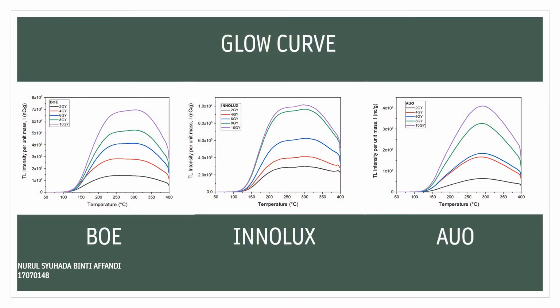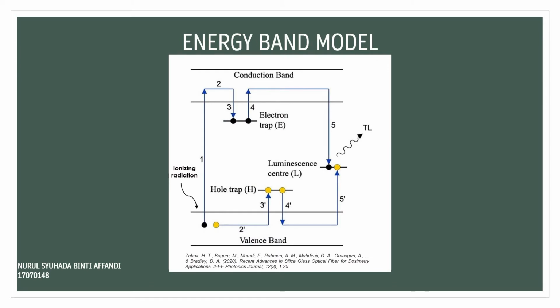There are a lot, only from the glow curve itself. The glow curve tells you about the electron traps. As the trapped electrons continue to be released from the traps, the TL intensity approaches its maximum and then decreases as the traps are depleted. Consequently, the glow curve shows the relation between the temperature used for releasing the trapped electrons and the intensity of the emitted light after the recombination of the released electrons.